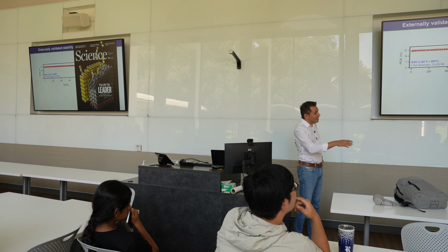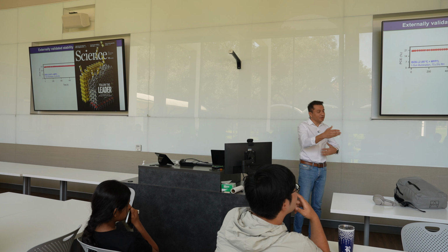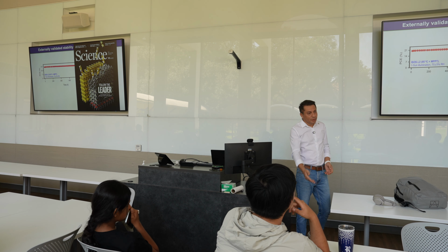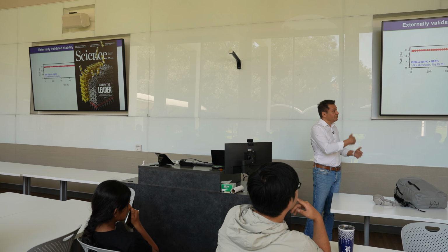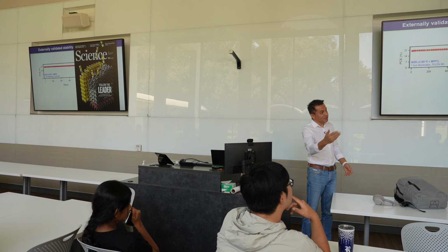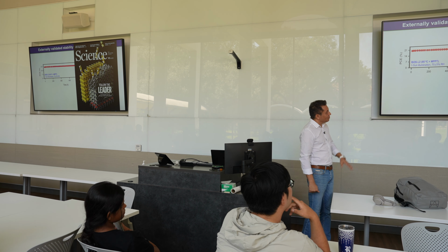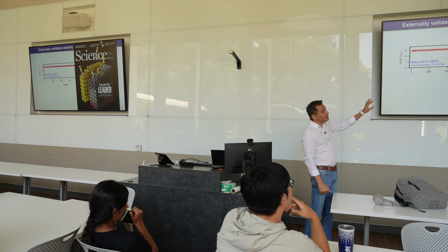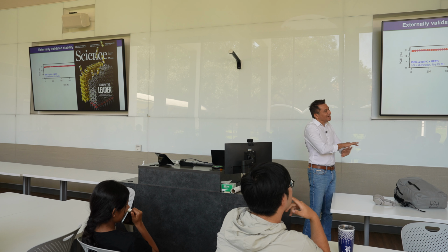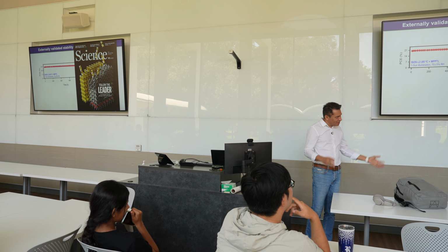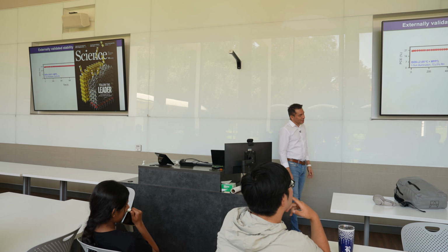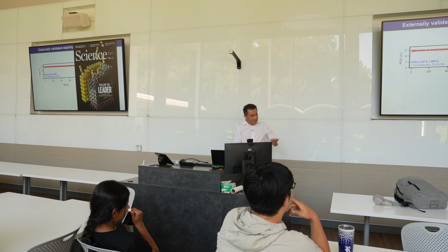Yeah, so these are all encapsulated, right? And so there are different types of tests you run. You could do a test which is 85 degrees C and 85% relative humidity. That's a dark test. But you could also do things like this, which are light and temperature, where you don't have any moisture. It's an encapsulation that people use. So there are different types of tests that you would run, right? So that one was done with encapsulation in ambient, but with encapsulation which does not let moisture or air in.